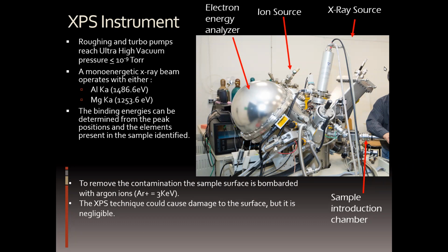Yeah, I was saying that these are the components. You have an ion source, you have the X-rays, you have the electron energy analyzer, and you have the chamber, the arm to introduce samples. We get to choose which X-rays we want. We can produce them with aluminum. This would be the K alpha X-rays, and this would be magnesium K alpha. And we can clean surfaces by introducing gas through these little tubes, could be argon gas, and we can use them to spray the surface and clean the surface.